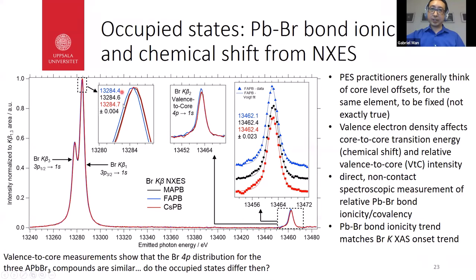And there are also differences between the three compounds, which was initially a surprise to me, because as somebody who started off doing electron spectroscopy, I thought all core level offsets were fixed. So this suggests that the valence electron density is actually different between the three compounds. And it suggests that the formamidinium lead bromide in blue has the most ionic lead bromine bond relative to the other two.